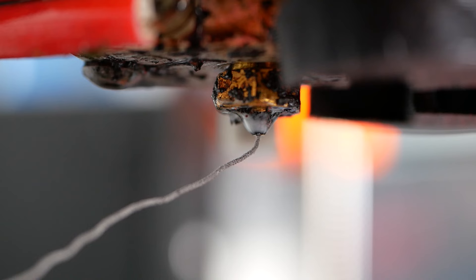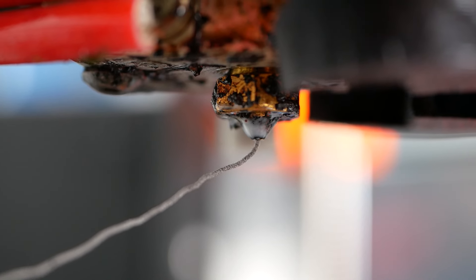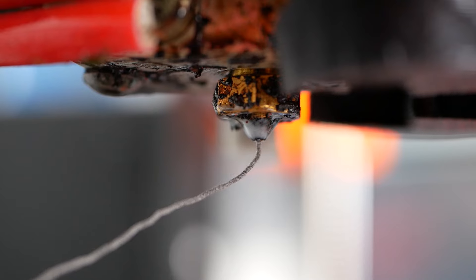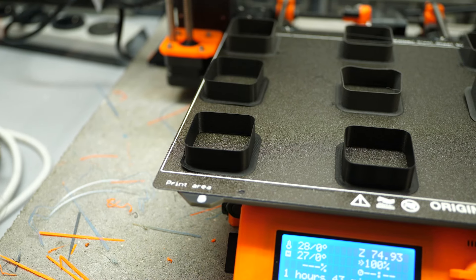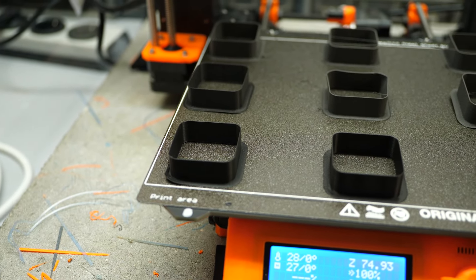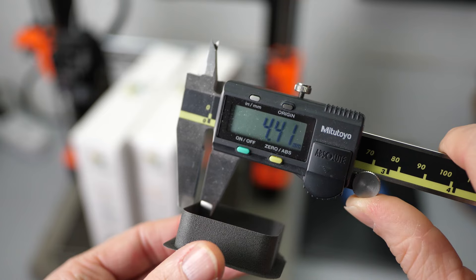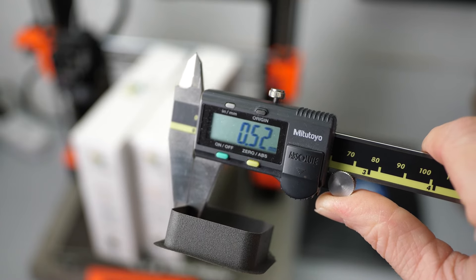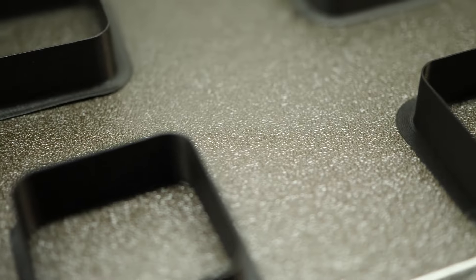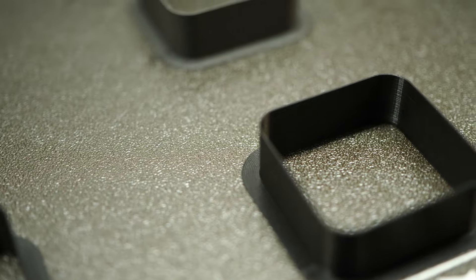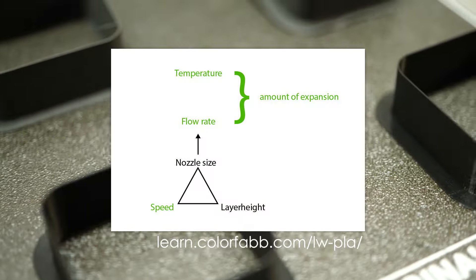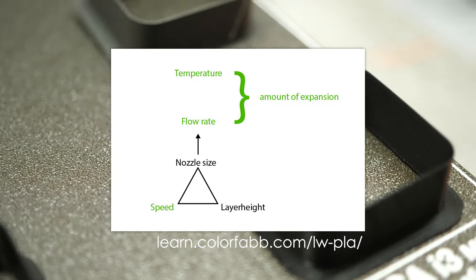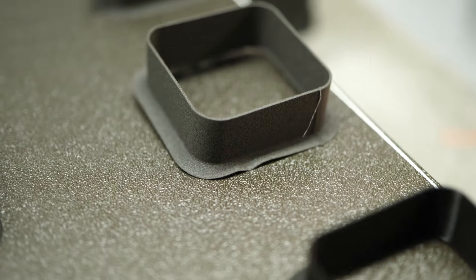When the material starts bubbling up, you need to reduce the extrusion amount because the volume increases and you would otherwise overextrude. To tune the extrusion amount, I printed sets of more single-wall parts where I measured the wall thickness to determine the reduction in the extrusion amount. You need to do that a couple of times because the degree of foaming is not only a function of temperature but also printing speed, material flow and so on.